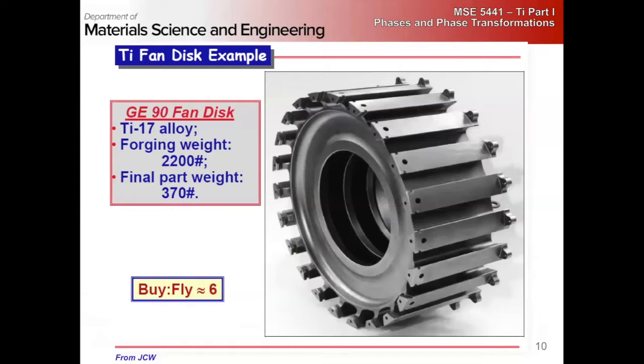This is Ti 17 as the alloy, but notice the raw forging weight before machining is 2,200 pounds. The actual part that flies is 370 pounds. So that means we're throwing away 5 times more material than we're actually using in the final part.